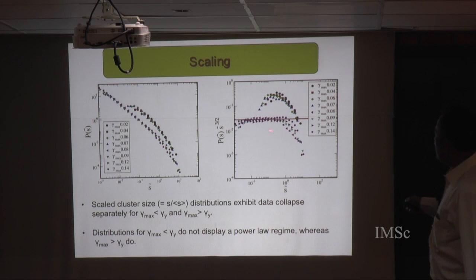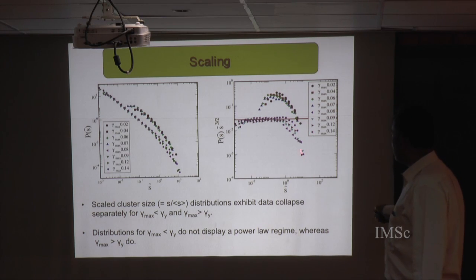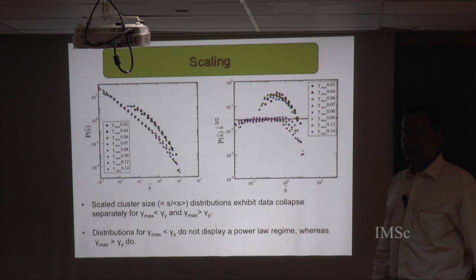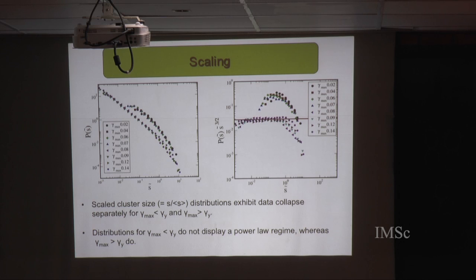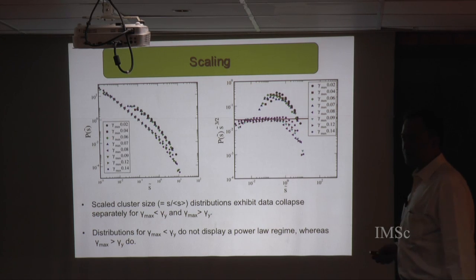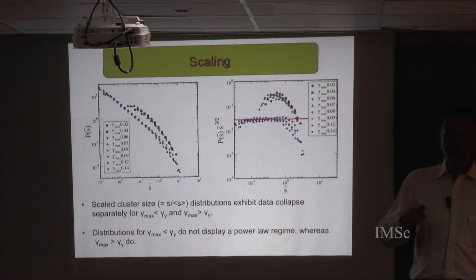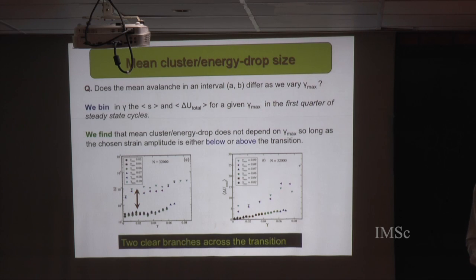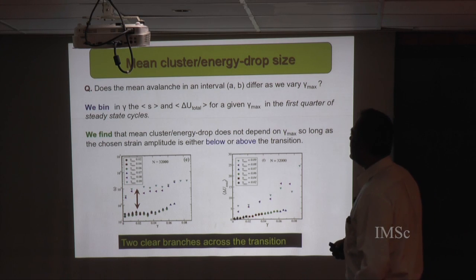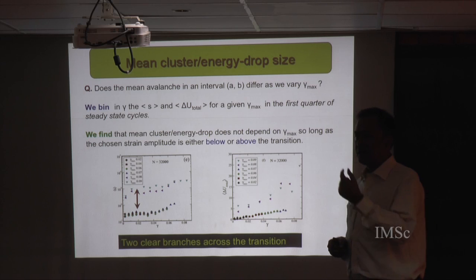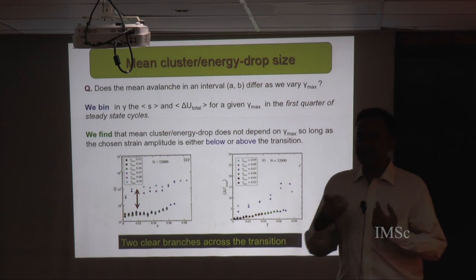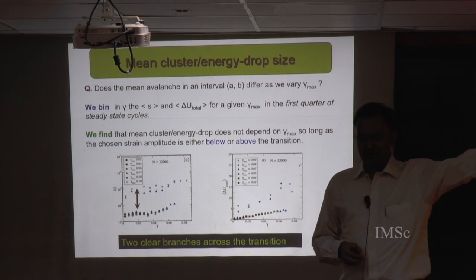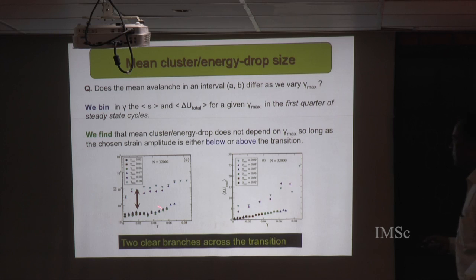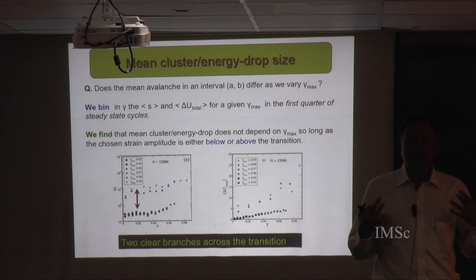You see that above the yielding transition, this s to the 3/2 with a cutoff that is determined presumably by the system size you're looking at is sort of a fairly well-defined behavior, whereas the function that describes data below the yielding transition is qualitatively different. Then you can ask whether the mean avalanche size in a given interval of strain values is different or the same depending on what your amplitude of strain is. And the answer is the data basically divide out into two sets.